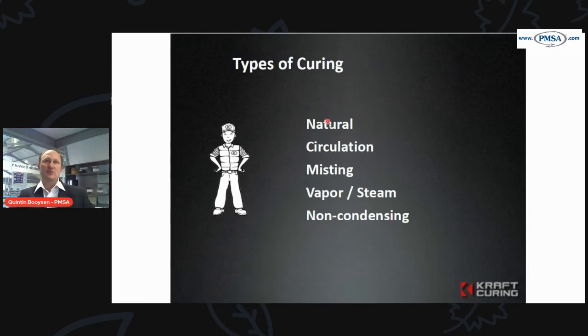Types of curing. We get natural curing, we get circulatory curing, we get misting, where we spray mist in the air, we get vapor and steam curing, where we're adding heat and energy in via vapor and steam, and we get non-condensing, which would be using indirect heating. So you'd have heaters that would heat the air, but not directly normally, and that would be non-condensing. So we'd be controlling the relative humidity in the chambers through having a controlled heat and normally working together with the misting to get a controlled environment.